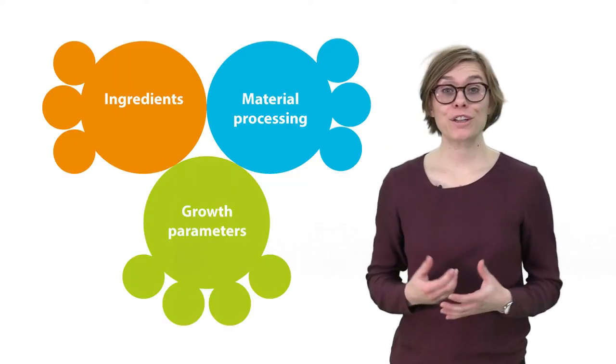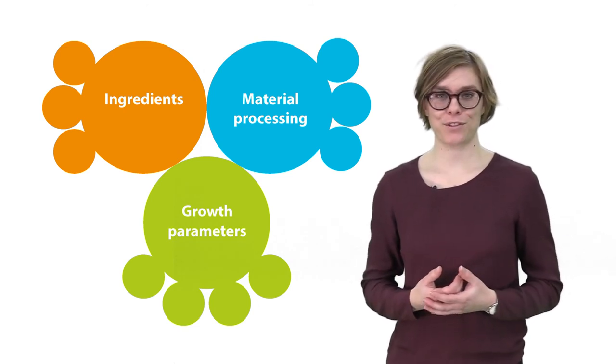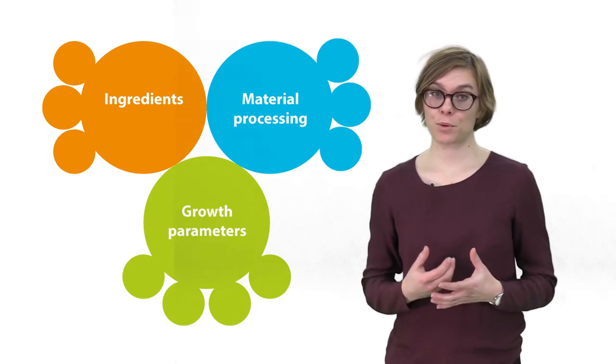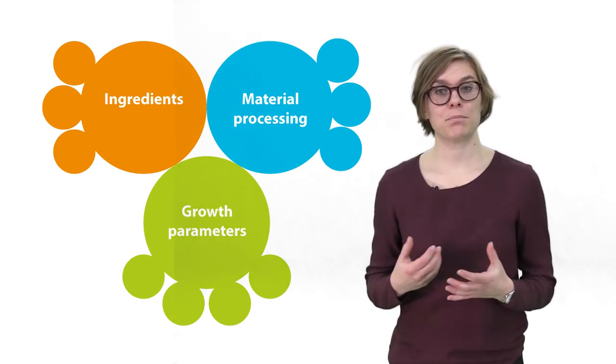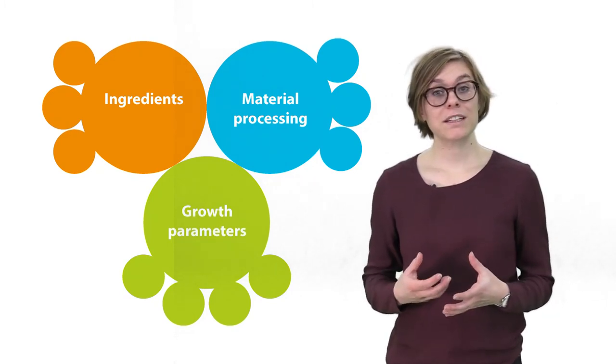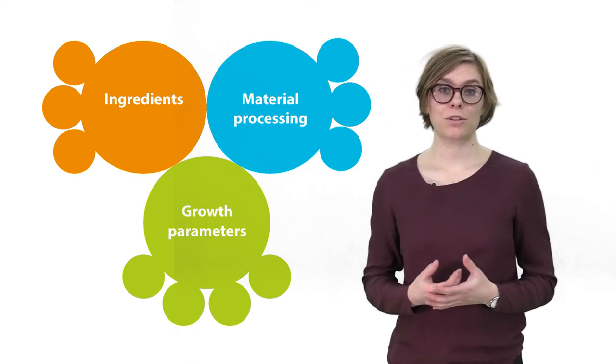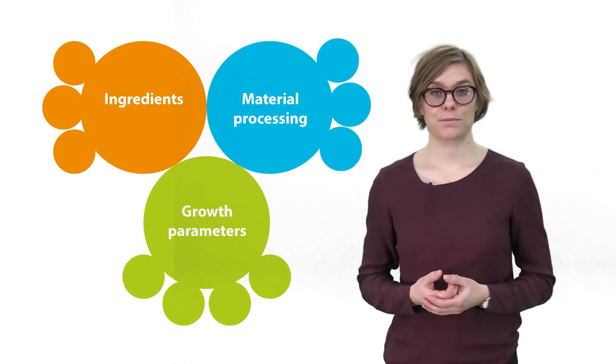We have mentioned all the important variables to be considered in the mycelium-based biocomposites process. All of these variables are important because different properties of the biocomposite are affected by them. For example, the density of the biocomposite depends on the type of substrate used. The thinner the raw material, the denser the final product. However, the growing parameters are essential to the actual growth of the composite. In this case, too low a temperature leads to a latent state of the mycelium and thus to limited growth.